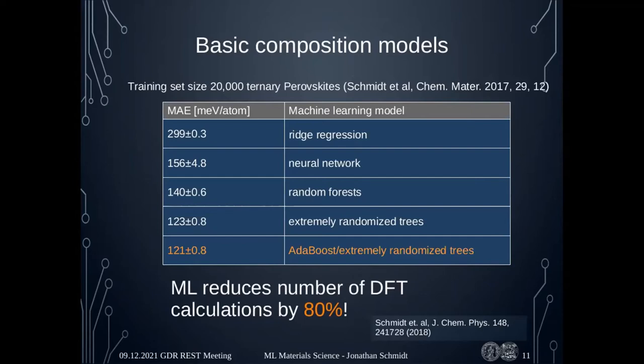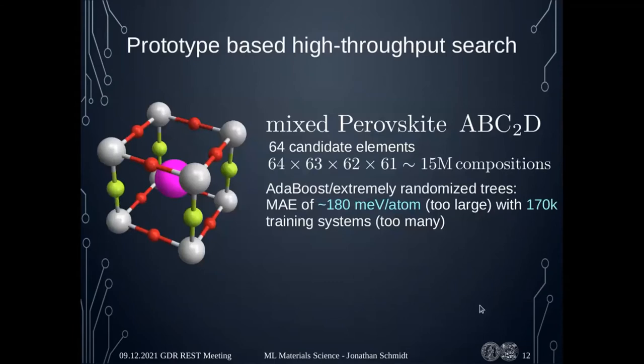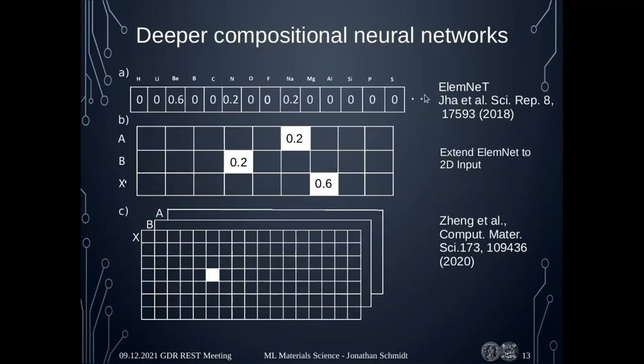We also tested this for about 20 prototypes and results were quite consistent. However, if we want to do quaternary perovskites — around 15 million compositions — even using a much larger training set of 170,000 systems, we still only get an error that is not good enough to differentiate stable from unstable compositions. We need better models. A main problem is that every time we do a prototype we need our own training set, since our features are based only on composition, meaning a lot of DFT calculations just to produce the training set.